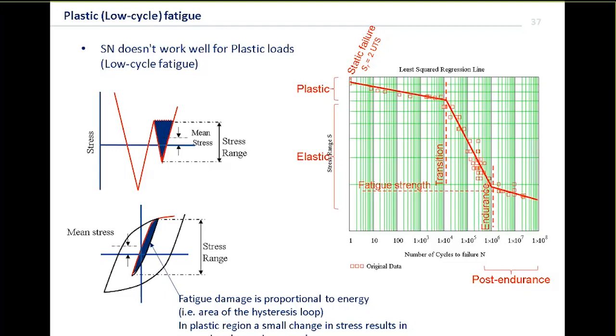You'll see that as the stress increases and we go plastic, a tiny change in stress makes a huge change in strain energy. So what we find is that the zone in the SN curve is very shallow, because we lose resolution. A tiny change in stress has a massive difference in fatigue life. If you're really interested in that, rather than using stress, it makes sense to use strain instead. A small change in strain will create a smaller change in life, and you need a big change in strain to get big changes.